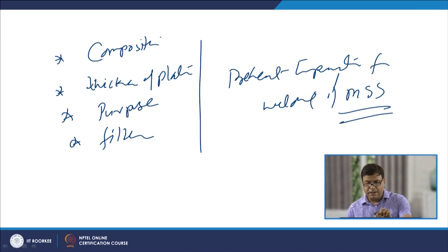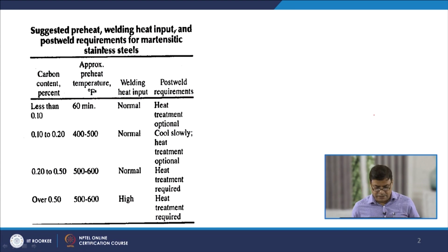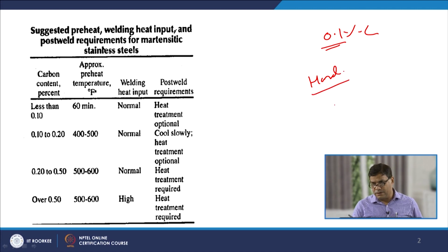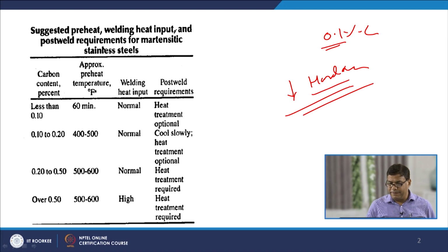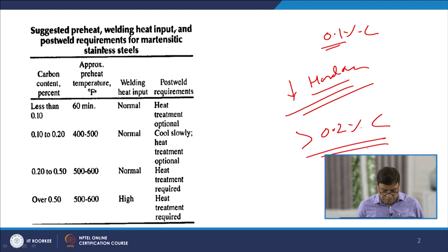If we do not preheat and if we allow the weld joint to cool down directly to room temperature, then the chances of cracking will be more, and this will happen especially when the carbon content is greater than 0.2%. We know that if the carbon content is less, like say 0.1% or even less, then the hardness of the martensite and the hardness of the heat affected zone as well as the weld metal will be low, and less hardness will be able to avoid the cracking tendency. So, the preheat is very crucial especially when the carbon content is greater than 0.2%. Apart from the composition, the thickness, the welding process and the restraint are the other factors that will be affecting the kind of preheat to be used.